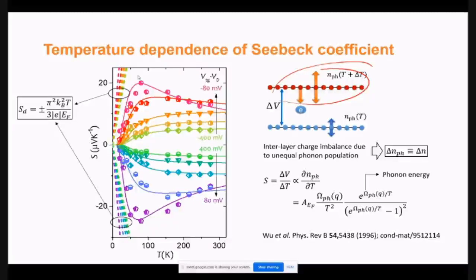Yeah, you're absolutely spot on there. And you're actually telling what we are now doing. What we are doing is inserting foreign layers in between the two graphene layers, which can jeopardize the lattice hybridization without jeopardizing the electrical coupling too much. See, the advantage here is that you can couple the two layers structurally, independent of the way you can couple them electronically. That's very interesting, and I'm going to end with that actually. That's what we call a complete bottom-up emulation of a thermoelectric material.